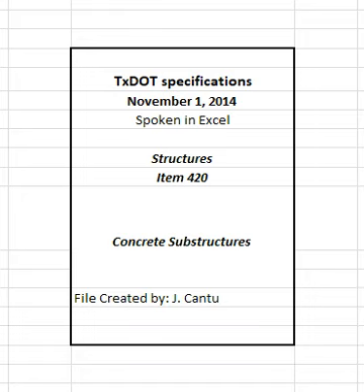4.7.4 Transporting concrete. Transport concrete by buckets, chutes, buggies, belt conveyors, pumps, or other methods. Protect concrete transported by conveyors from sun and wind to prevent loss of slump and workability. Shade or wrap with wet burlap pipes through which concrete is pumped as necessary to prevent loss of slump and workability.